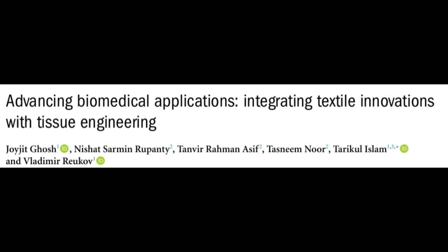That requires getting blood vessels in there, which seems incredibly difficult. Vascularization is indeed one of the biggest challenges in engineering larger, thicker tissues and organs. The sources highlight efforts using angiogenic scaffolds loaded with growth factors like VEGF and PDGF, leading to a threefold increase in capillary density in studies. Okay, encouraging vessel growth. Combining textile scaffolds with microfluidic designs and perfusion bioreactors is also key to creating the necessary intricate blood vessel networks to keep the engineered tissue alive and integrated. Reducing inflammatory responses using surface modifications and hybrid materials is also crucial for successful long-term implantation.